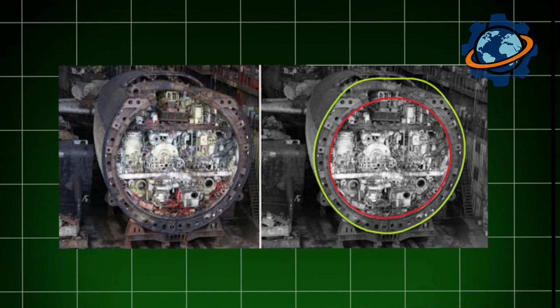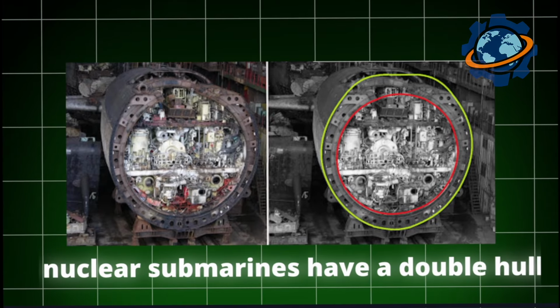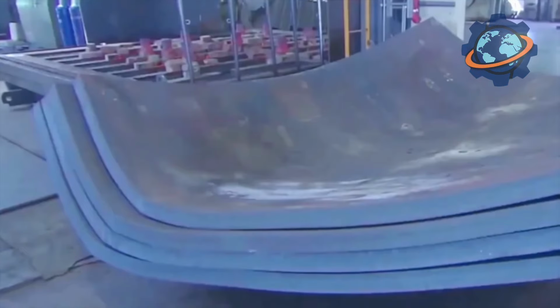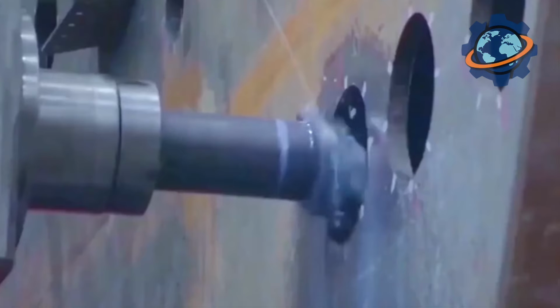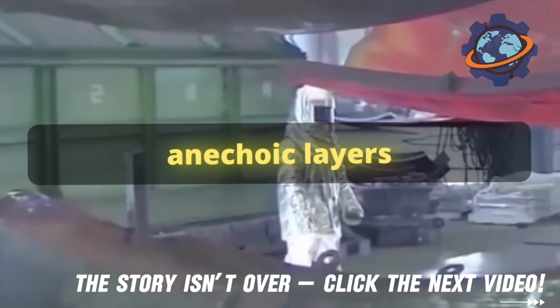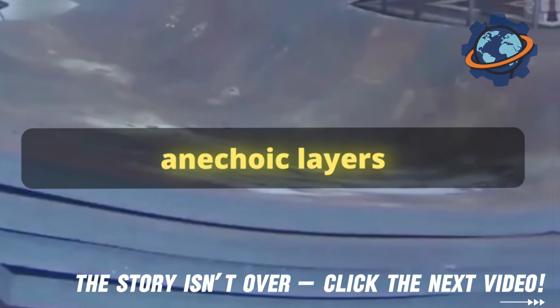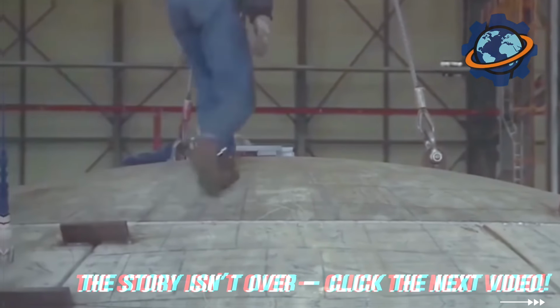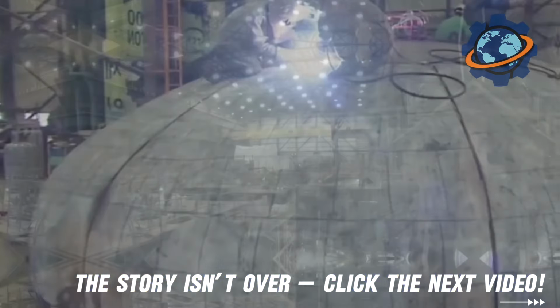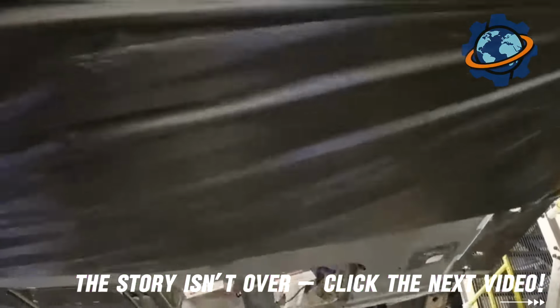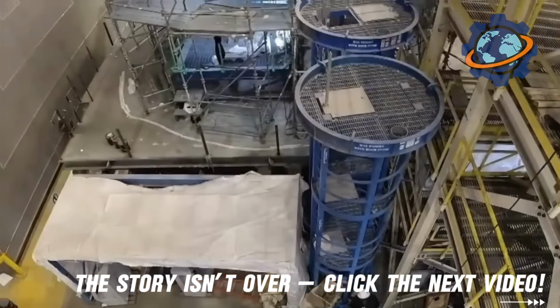Most nuclear submarines have a double hull. A strong inner hull withstands high pressure at great depth, while an outer hull provides a streamlined shape, improves hydrodynamics, and helps reduce the likelihood of detection. Ballast tanks, which regulate the submarine's buoyancy, are usually located between the hulls. To keep the submarine as stealthy as possible, it is covered with anechoic layers. These are polymer tiles that absorb sound waves, as well as composite materials with micropores that reduce the acoustic signature, and noise-dampening coatings applied to the propellers and power plants.